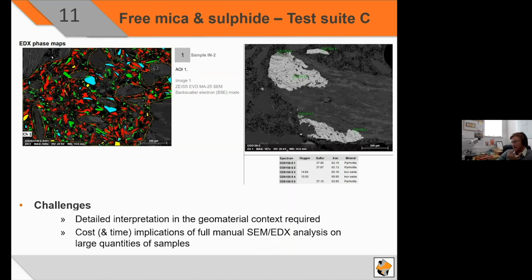If we look at test suite C, this focuses on analysis by SEM. On the left-hand side, we have free mica analysis. This is undertaken by elemental mapping of the binder, with the geologist then using image analysis to interpret, remove things which influence this figure. That includes other fine minerals such as feldspars, which can distort the free mica reading, as well as free mica, which is over 65 microns in size.